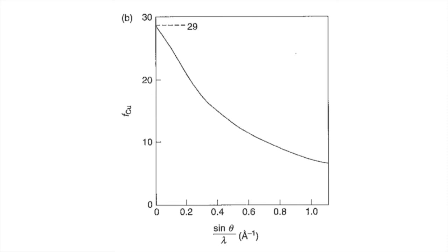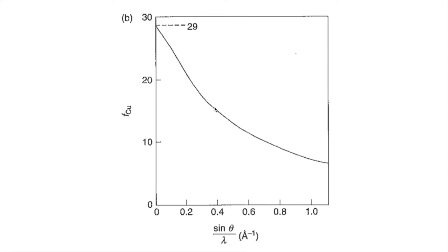And so we have the maximum intensity possible of the scattered beam compared to the incident beam. But as the angle increases, you notice that the atomic scattering factor decreases. That means we have more relative phase differences introduced, so destructive interference goes up, and therefore the atomic scattering factor goes down. So the more angle that we have, the more destructive interference caused by these phase differences.